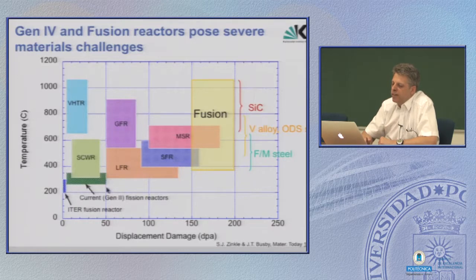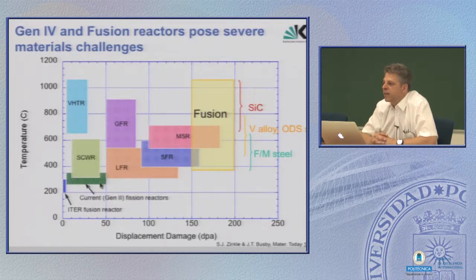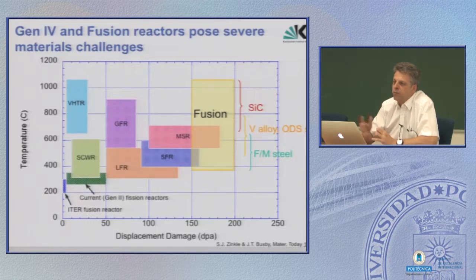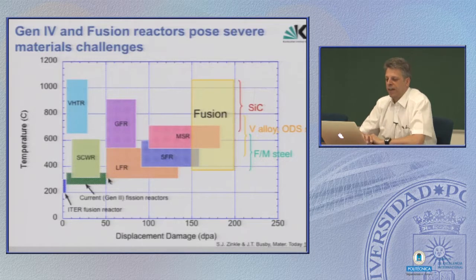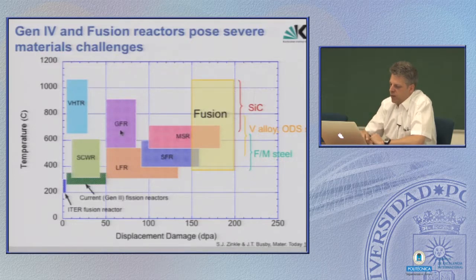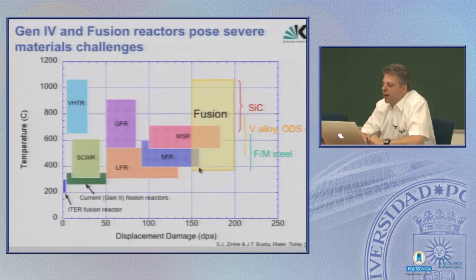Current operating fission reactors are in this area. Most often they are pressurized water reactors, so they end up at around 300-something °C, or in some cases they are liquid metal cooled, then the temperature range is higher. These are the 5 plans for generation 4 reactors, which we don't have to go into detail here, and some of them overlap with the fusion power plant requirements.